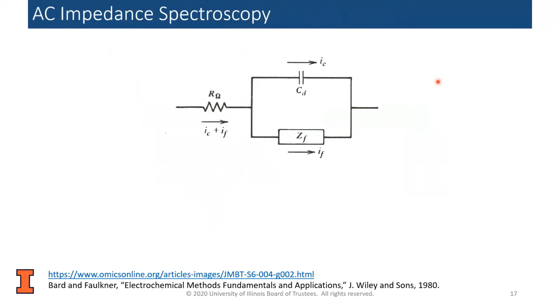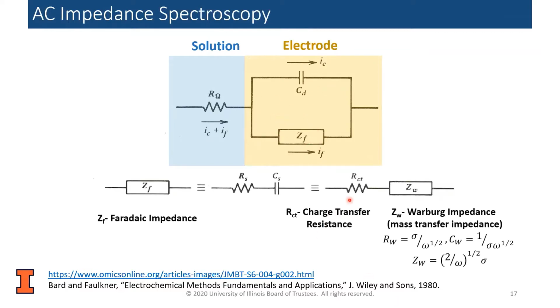So now I'm going to introduce to you another technique that is very common to the study of batteries. And many of you may not be familiar with this. This is a technique known as AC impedance spectroscopy. It turns out that you can model electrochemical systems with electronic circuits comprising common elements like resistors and capacitors. Some of these components will be due to the solution, and some will be due to the electrode. The electrode components consist of a Faradaic impedance, which consists of a charge transfer resistance, and another component known as a Warburg impedance, which relates to the diffusion. We'll also have another component in the electrode, which represents the electrical double layer between the solution and the electrode. That basically indicates that we have some polarization right at the surface of the electrode.